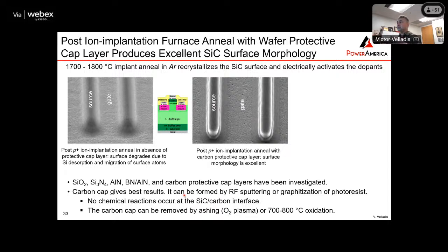So all you need to do is put resist on your wafer, and then when you put it to 1800 degrees or 1700 degrees, the resist will basically become carbon. It will carbonize. So you will have graphene, and that will be a carbon protective layer. So you can see here when there was no protective layer, basically the surface looks very poor because the silicon desorbs and migrates from the surface at a faster pace than carbon. Once you cover it with a carbon layer, then you don't have this desorption problem, and the wafer looks good.